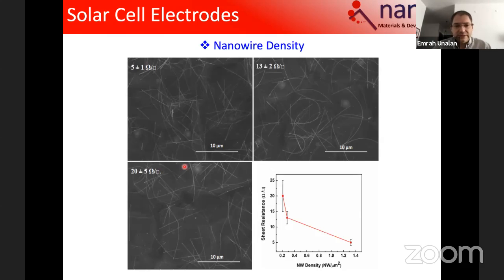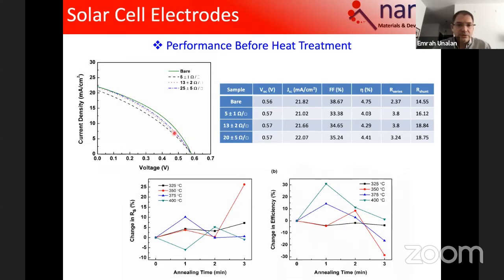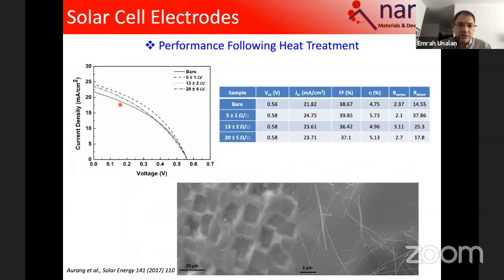We tried 3 different densities. When we directly coat on it, our cells with silver nanowires were not working properly, but similar to silver fingers, you need to apply a heat treatment for the ohmic contact formation. And when we put these materials, we monitor this with the series resistance changes. So if you heat this up to 400 degrees C in a very short time, like a minute or so, your series resistance gets improved and the device characteristics get improved. And there are also some plasmon effects that we discussed in the manuscript. But certainly, as I said, this needs to be improved further with an anti-reflection layer and a passivation layer, with which I believe we will get much improved device characteristics by using front surface silver nanowires instead of silver fingers.